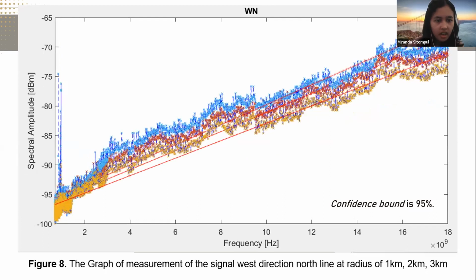Okay, this is the measurement of signal west direction north line, and from the graph we can see that the spectral amplitude is in the range of minus 65 decibel to minus 100 decibel. And from the measurement of three data with distance variation, it can be seen that the data obtained are similar, and this shows that there's no material around the measurement point that interferes with the measurement at a distance of 1 until 3 kilometers. And we can see that all three data have confidence bounds value of 95%.